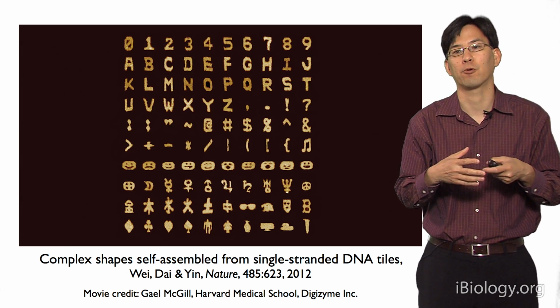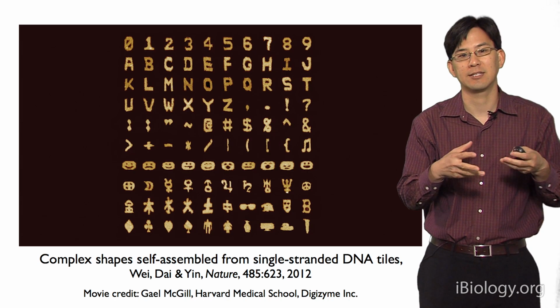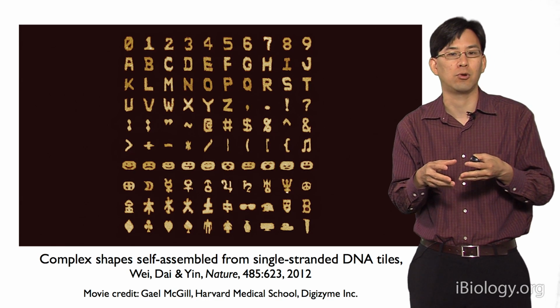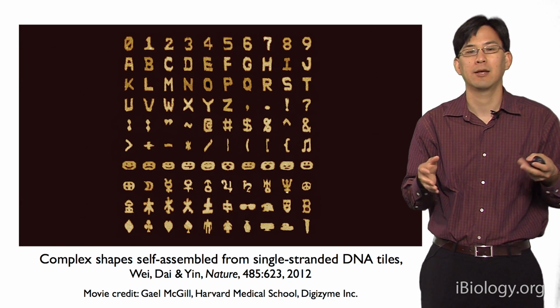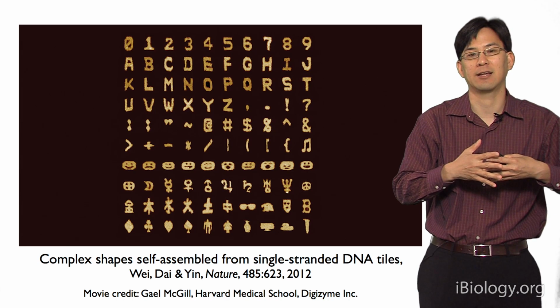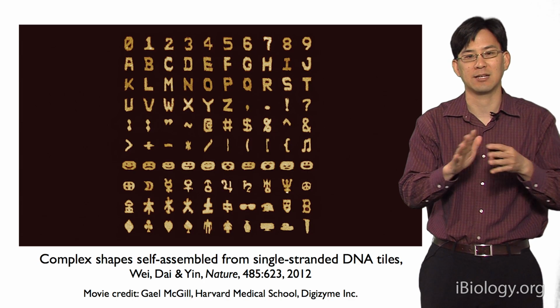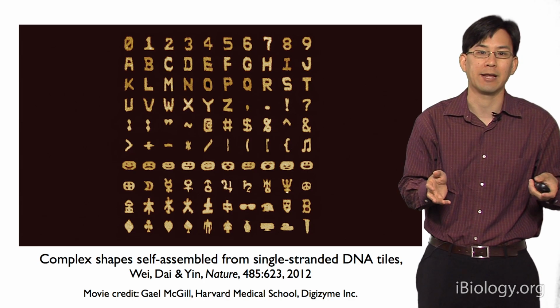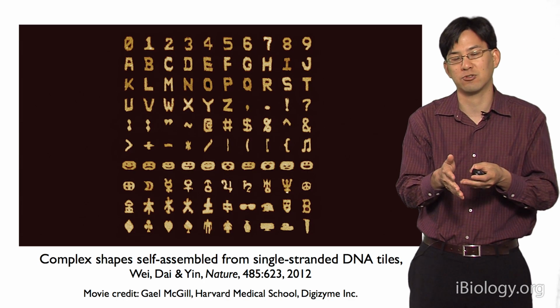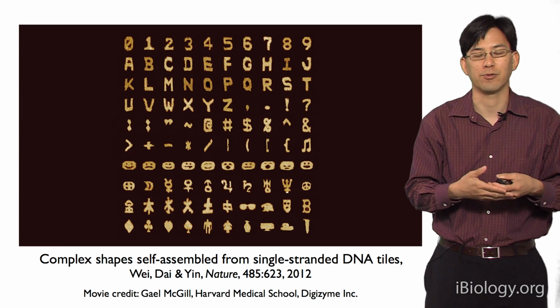So we think that a robust design principle for programmable self-assembly is to try to build your system so that nucleation is slow or controlled. So we can see with DNA origami, we can now envision those long scaffolds as controlled seeds. If we're adding an excess of the staple strands, then we know the number of seeds is basically the number of those long strands that we're adding. And in that way, you never run out of the building blocks. In this case, with the single-stranded tiles, it's because that nucleation event is slow and the growth is fast.